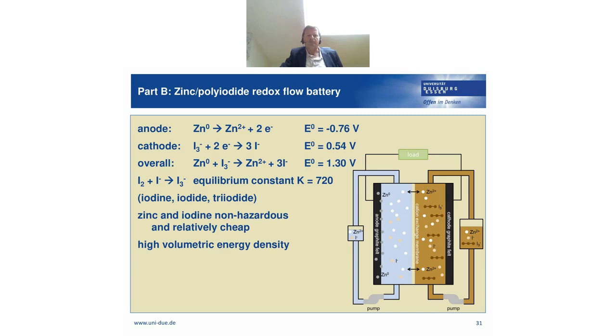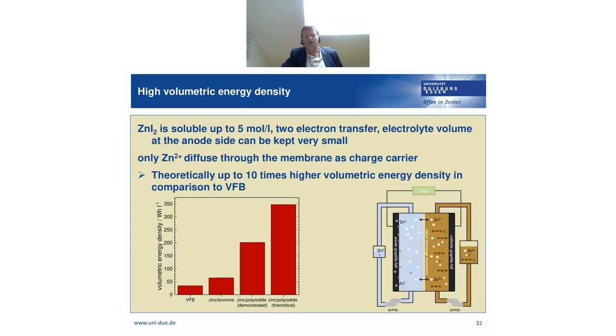Zinc and iodine are non-hazardous, and especially zinc is quite cheap. Iodine is a little bit more expensive, but less expensive than the vanadium, for example. And this battery chemistry allows for a high volumetric energy density. As you can see here, we start generally by using zinc iodide, and zinc iodide is soluble up to 5 mole per liter. So you can compare this value with around 1.6, 1.7 mole per liter of vanadium salts that can be dissolved in acid.